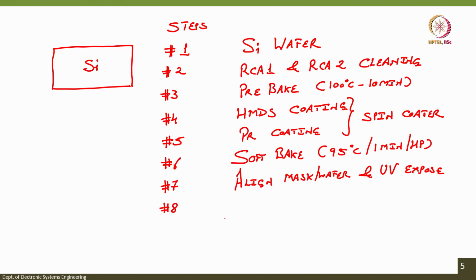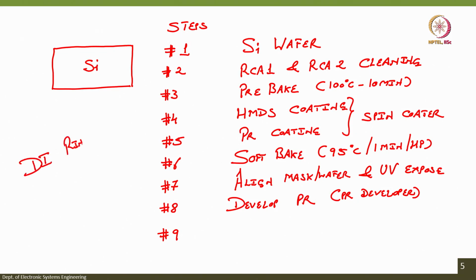Next step, you load the mask, align and expose. Then unload the mask, and after unloading you have to develop. Develop what? Develop the photoresist in photoresist developer. Whenever the wafer is exposed to any chemical, there is always a step of DI rinse, deionized water rinse. So, after the PR developer there is a DI rinse followed by hard bake.